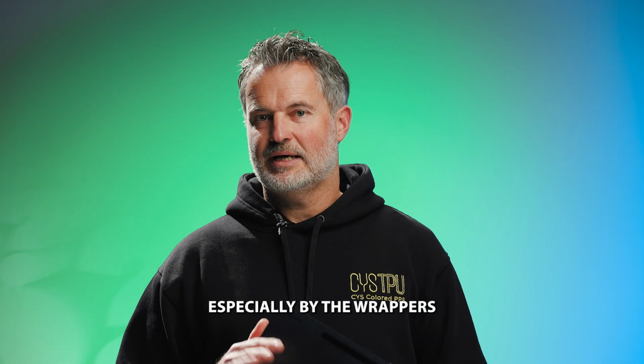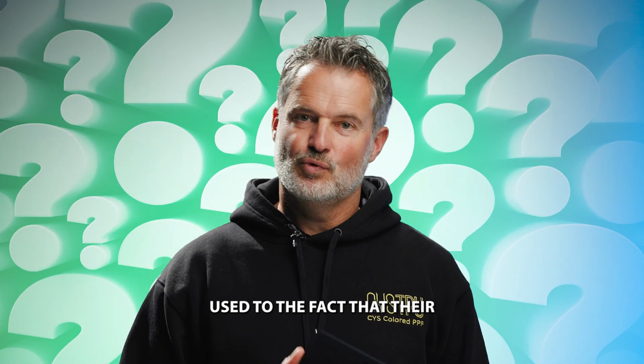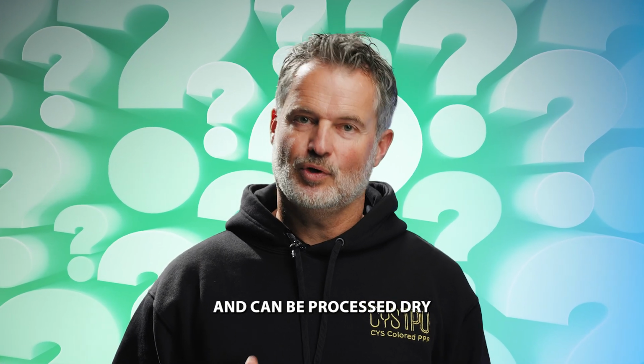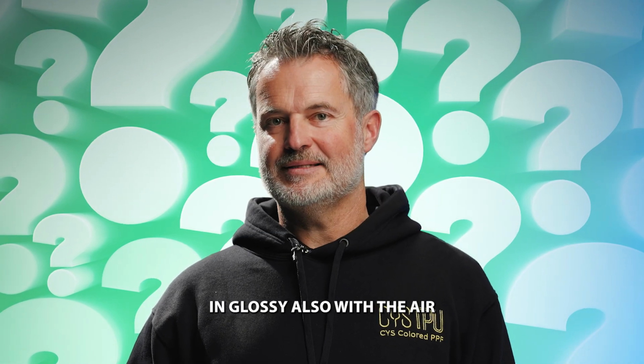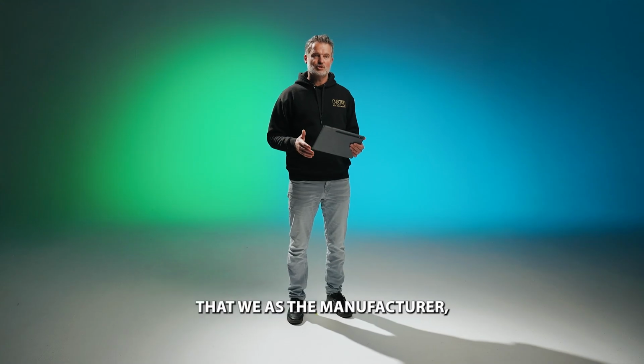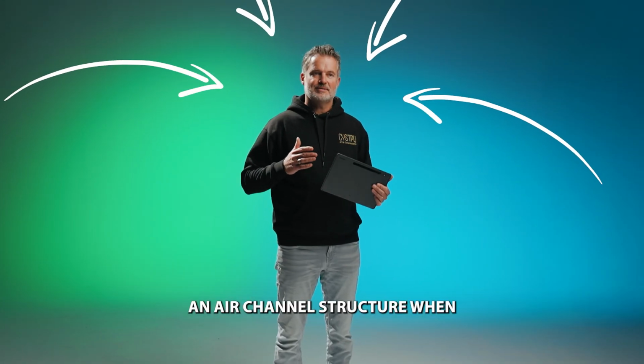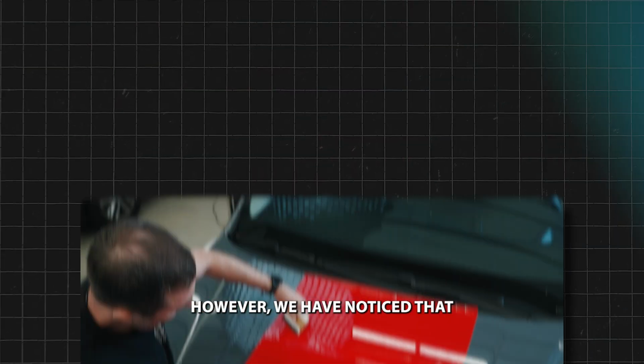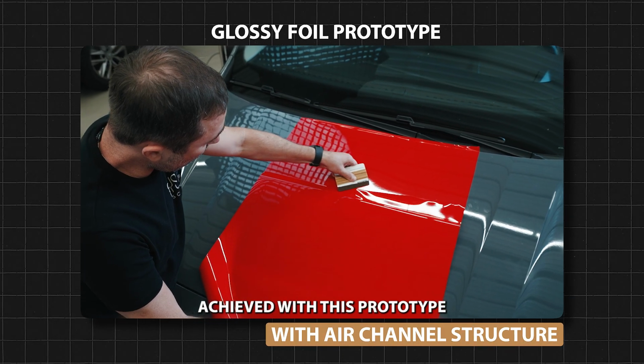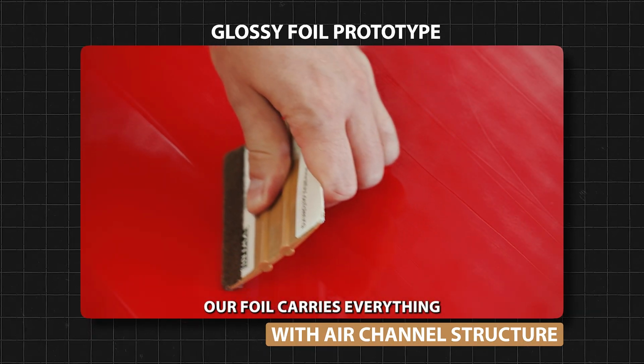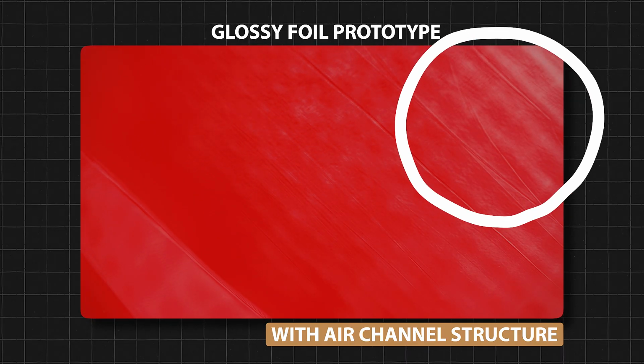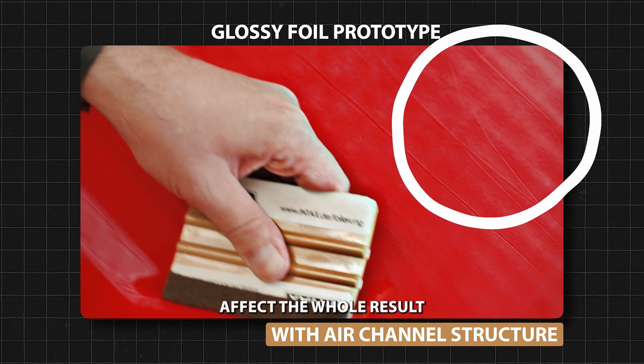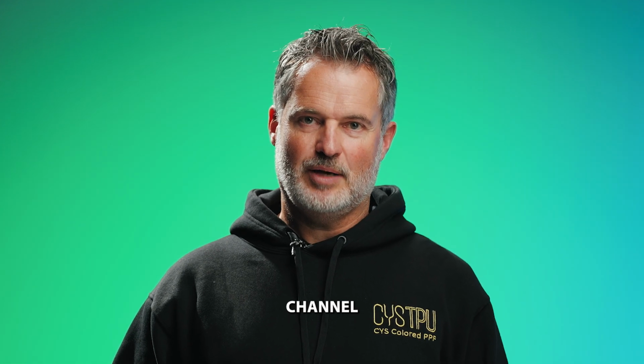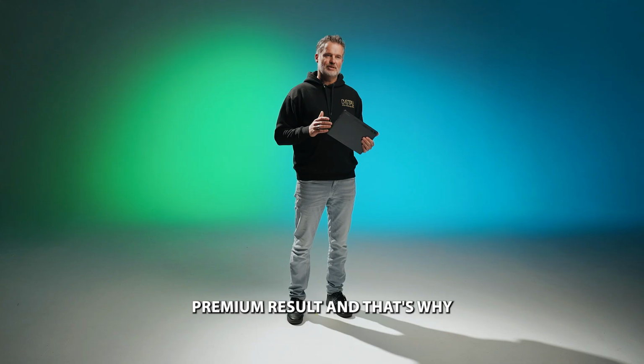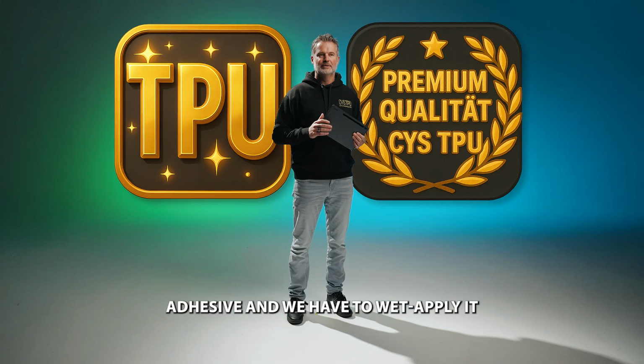We are asked again and again, especially by the wrappers who are used to the fact that their foils all have air channel structures and can be processed dry: why don't you make the foil in glossy also with the air channel structure? Basically, it was the case that we, as the manufacturer, first had glossy foil with an air channel structure when developing the foil. However, we noticed that perfect results cannot be achieved with this prototype. The extreme gloss level of our foil carries everything to the top, causes traces to form, and affects the whole result. It might be easier to process glossy foil with an air channel, but we want the absolute premium result. And that's why the glossy film has to have the smooth adhesive, and we have to apply it wet.